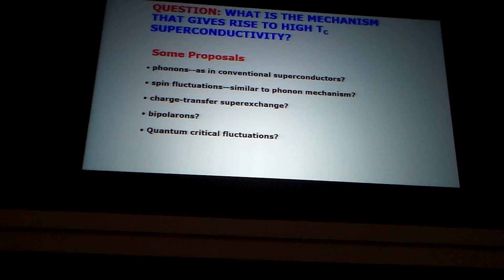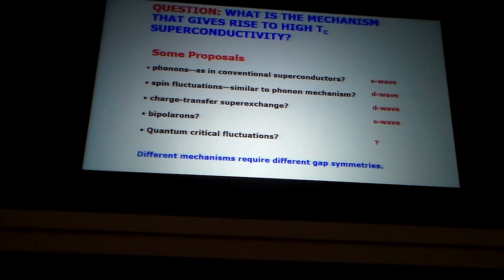Okay. So, of course, there's many proposals, because theorists are very creative. And this is only a small list of the proposals that have gone on. But phonons pretty much can be ruled out because of the following reason, that each proposal has a different orbital symmetry with a superconducting wave function. So, for example, phonons are pretty much expected to be S-wave or L equals 0 orbital part of the superconducting wave function. But what's been found in the cuprates is that the order parameter is D wave, L equals 2. I'll show you in a minute what that means.